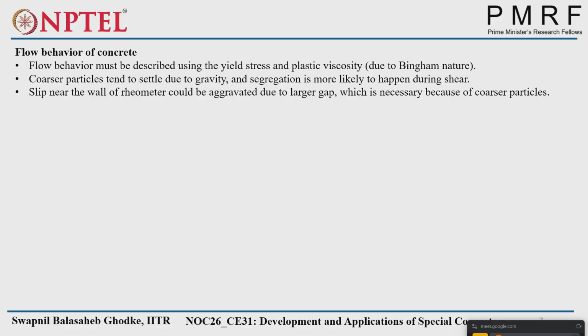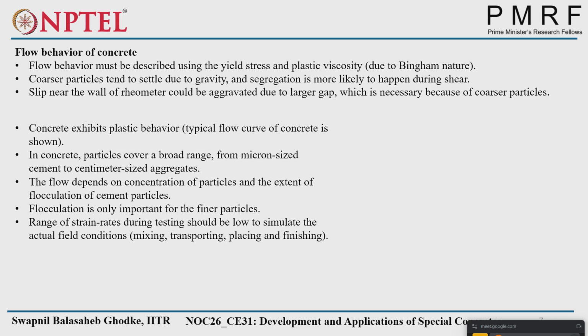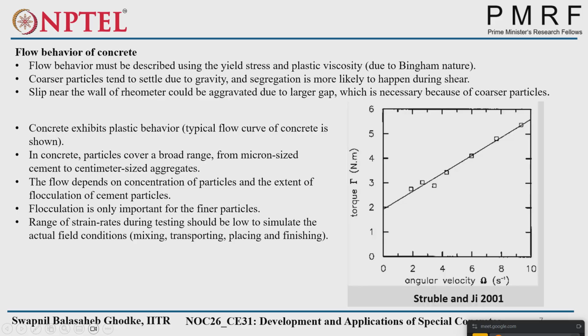So that's why we have to provide the minimum shear rate in the case of concrete, which will mimic the actual procedure or actual protocol of the mixing. So concrete exhibits plastic behavior. If you see, this is the torque versus angular velocity, that is rotational speed. We get the data, we plot it, and we see this intercept, which we call tau zero. The slope of this graph we get as the plastic viscosity, that is eta p. We have the shear rate, at which we have rotated that material, that is gamma dot, and we get the whole equation for that particular material.